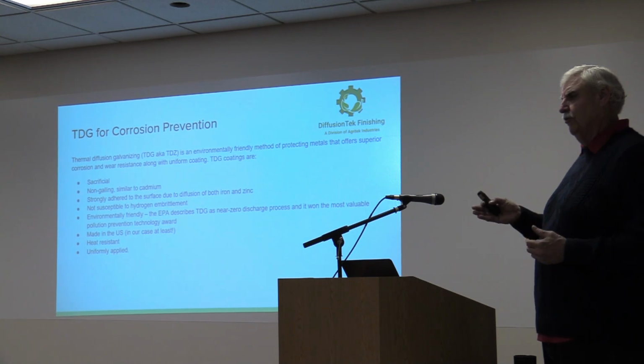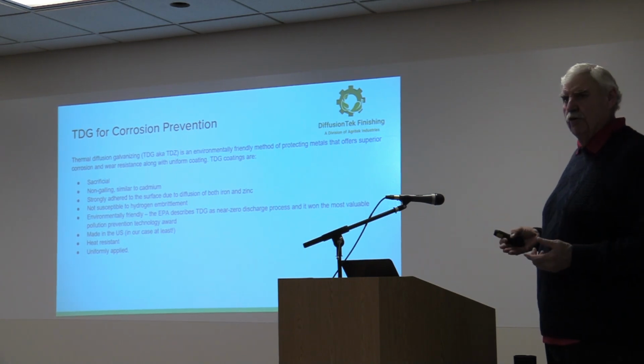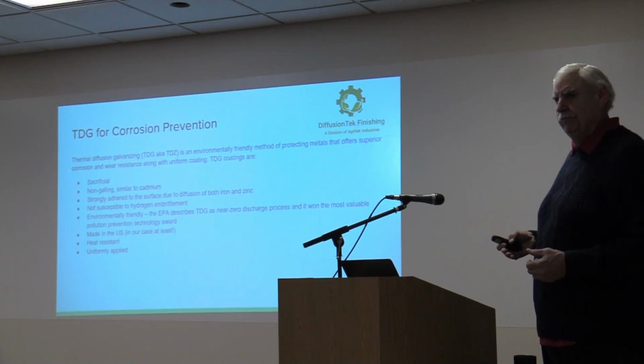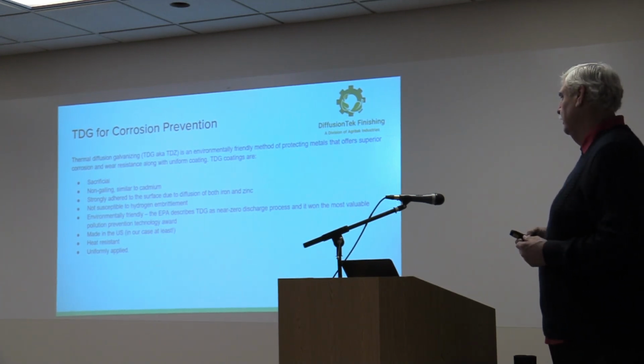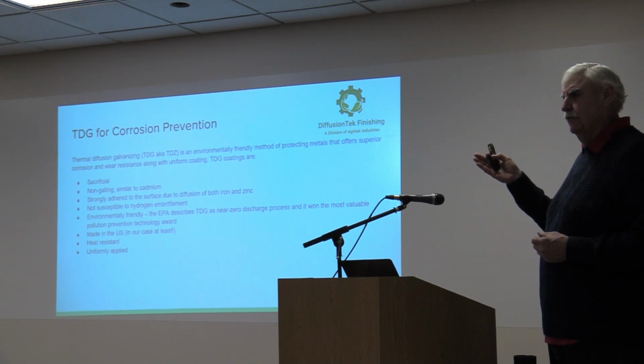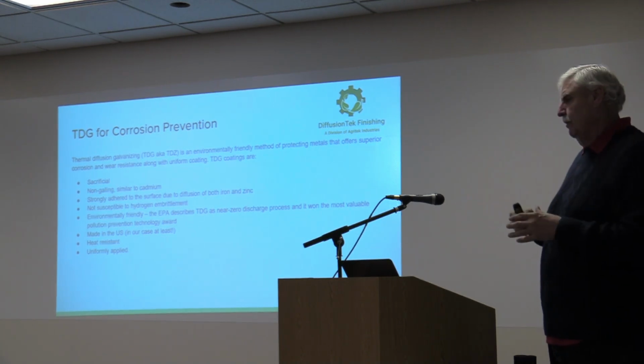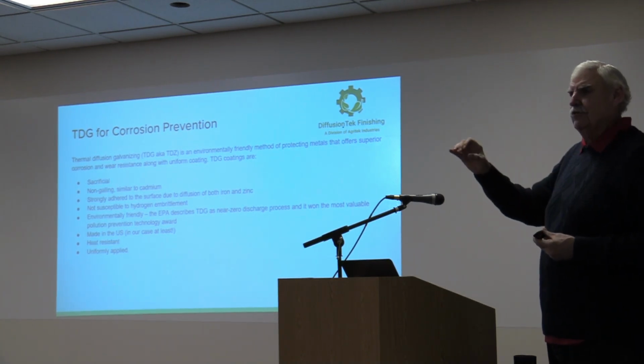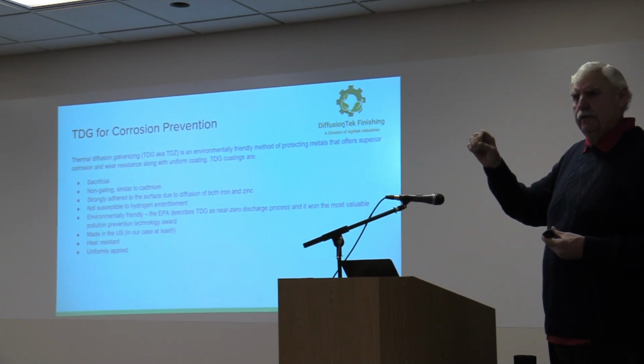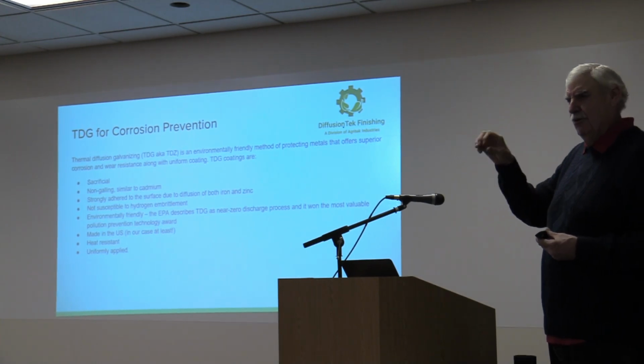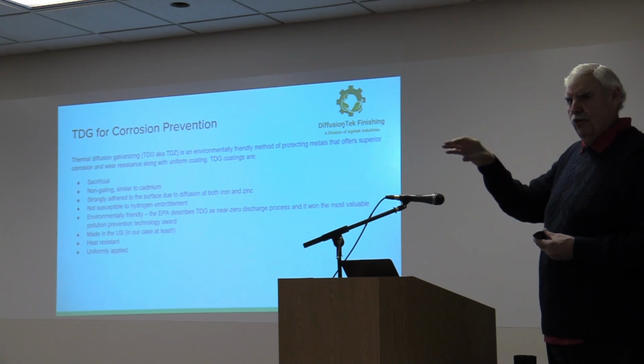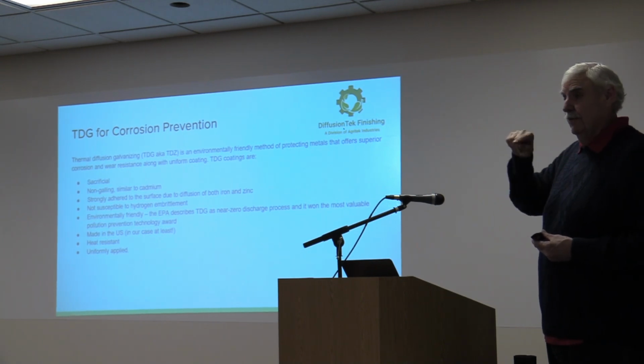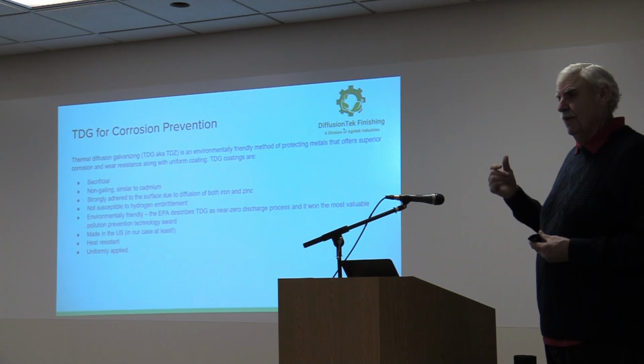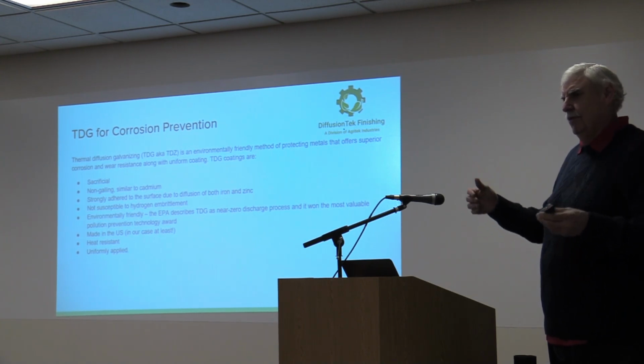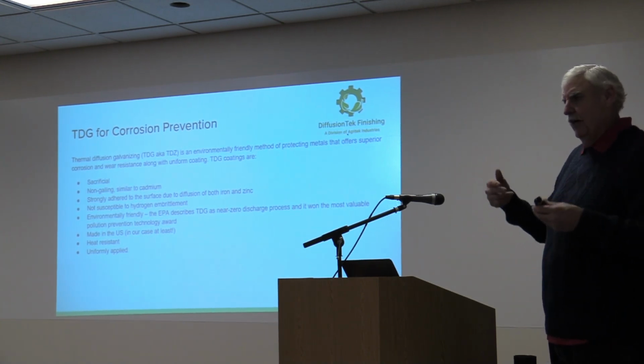It's heat resistant. So this coating is resistant up to 1200 degrees Fahrenheit. So it doesn't deteriorate up to that temperature. So it's pretty good. And it's uniformly applied. Because it's a vapor, if you were to try to plate something, if you're familiar with plating, you have to basically throw those electrons inside, let's say, a tube. You're not going to plate inside that tube very well. In our case, it's a vapor. It'll go all the way around, inside, everywhere.